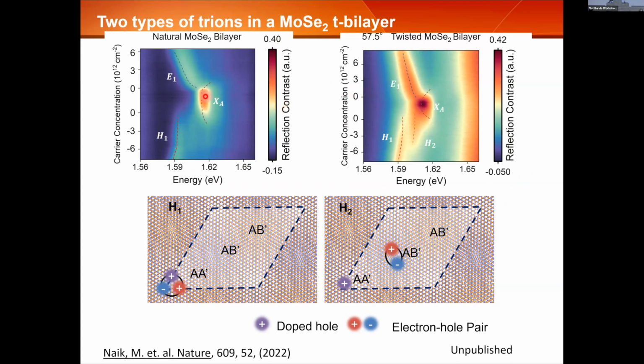And on the electron doping side, you can't really describe the system with a simple trion picture anymore, because there's a gradual energy evolution. So we started adopting the language of polaron. I think there's some really interesting science associated with the electron hole pair coupled to a Fermi sea. And then on the hole doped side, because the valence band is much flatter, the holes are very much localized in the supercell at particular locations.